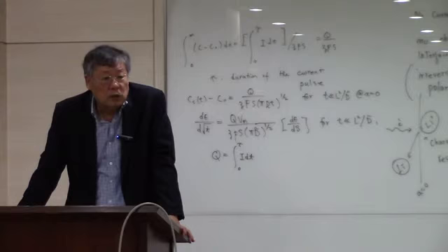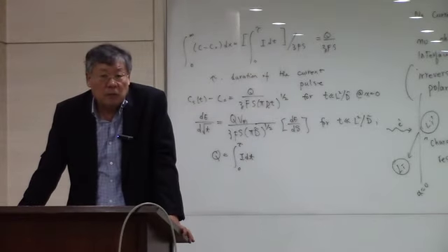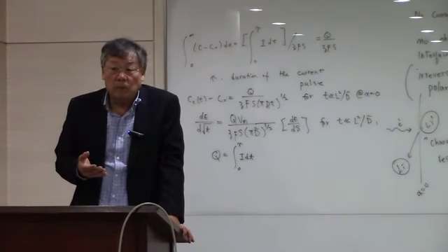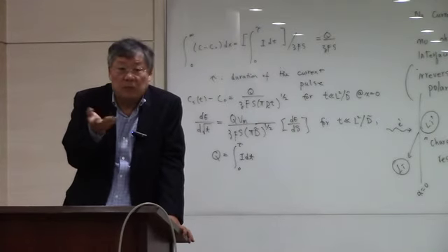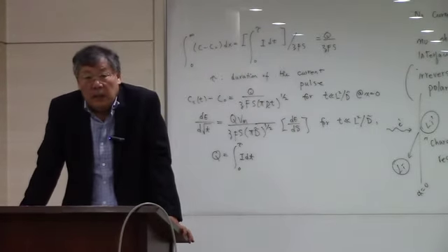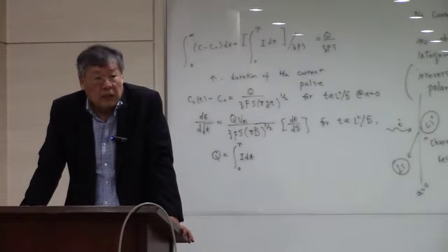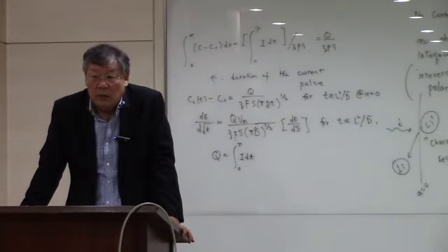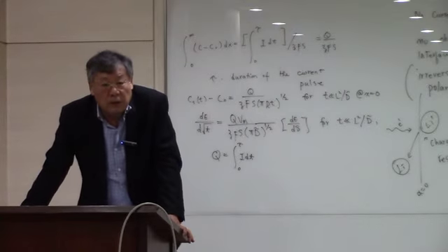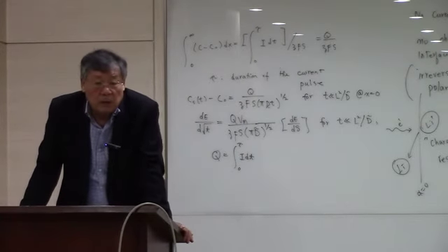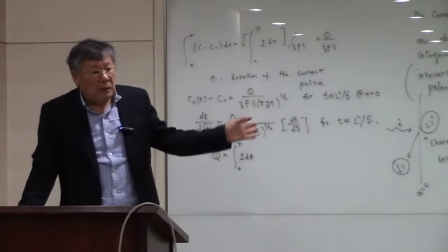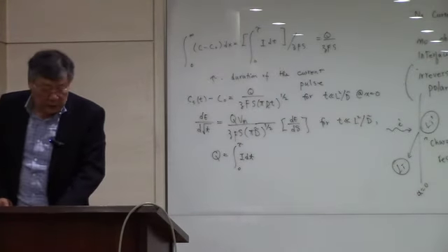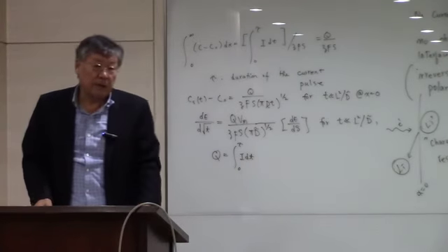So what you do is you make a cathode material in a thin film form so that the distance to be equilibrated is very short, like less than 1 micron. Then it can be equilibrated reasonably quickly so that you can exercise this technique very easily. Okay?